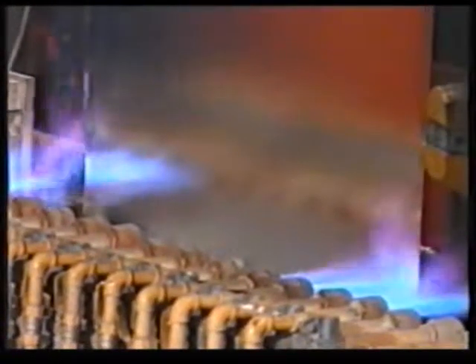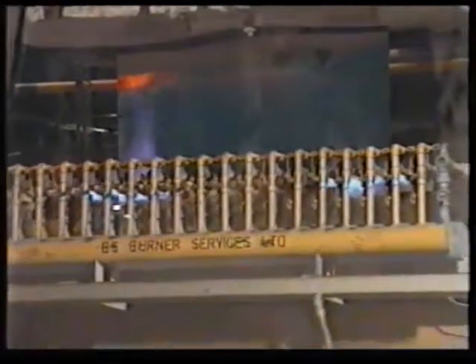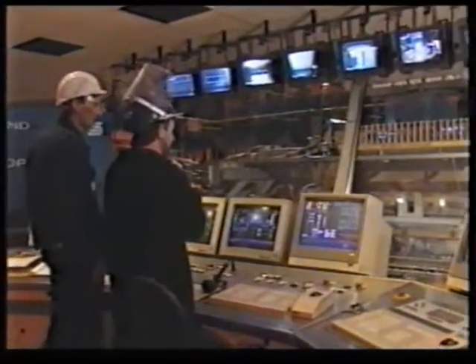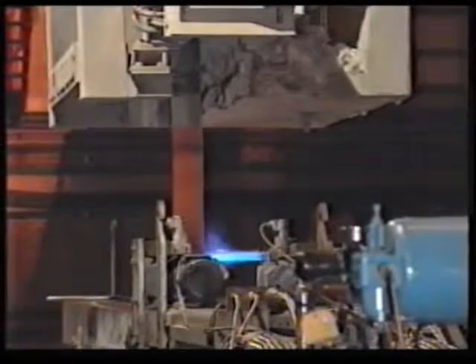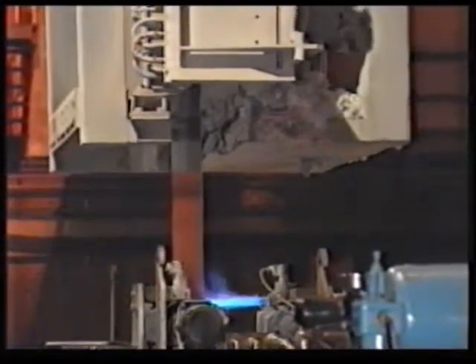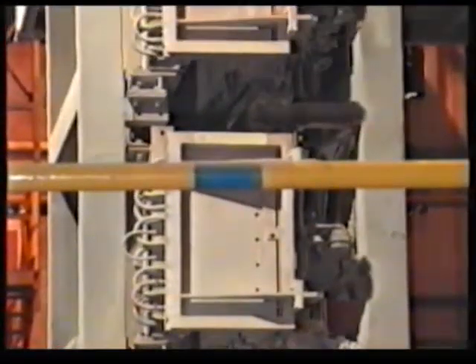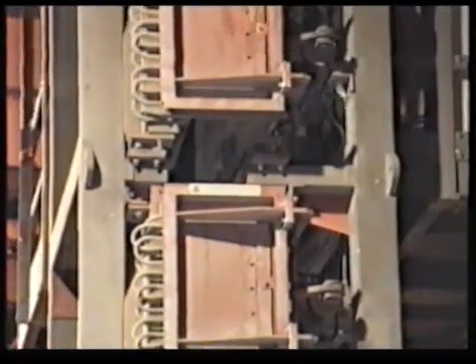Double-sided zinc-coated steel is produced by a different process, and seeing how this is manufactured takes us to British Steel's Llanwern plant in South Wales. Here, sheet steel is immersed into molten zinc at 455 to 465 degrees centigrade in a process known as hot dip galvanizing. Then, by careful heat treatment within a vertical furnace located above the zinc bath, the zinc coating is converted into a layer of iron-zinc alloy.